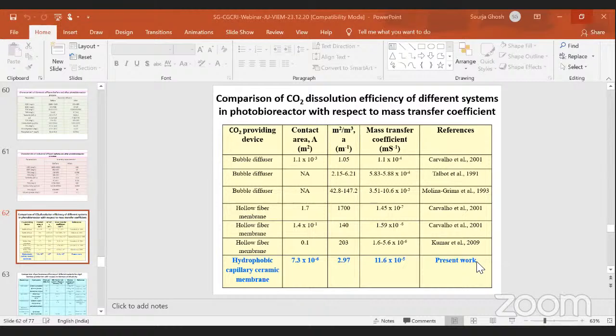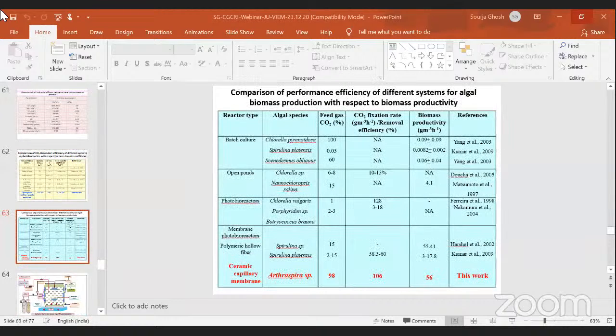So when we compared our membrane's efficiency in terms of the CO2 dissolution in the photobioreactor, we found that we are in a very encouraging position. This is the hydrophobic capillary ceramic membrane, and this resulted in a high value of mass transfer coefficient. So we are quite competitive with the hollow fiber membrane system on the higher side, and just below the bubble diffuser rate. So our objective is to achieve a higher mass transfer rate, and we are working on this area. This is the comparison of the biomass production and productivity capacity.